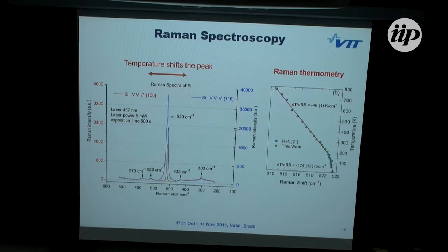And as shown later, we use this Raman spectroscopy also to measure the temperature. This same peak also shifts with temperature, and the shift can be calibrated, and then you can use this peak shift as a thermometer to measure the temperature locally on the spot on the membrane to get the thermal conductivity, but I'll come back to that later.